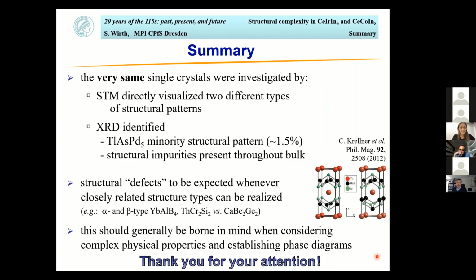Yes, actually, you have to be a little bit careful here. What we saw over the course of many years is that little nuances can pretty much influence the cleaving behavior. I have shown you that the cerium cobalt indium-5 actually cleaves pretty easily, at least along the 001. But in the example of the 122 structure, for instance, we have lots of experience with ytterbium rhodium 2 silicon 2, which cleaves nicely. But if you go for cerium copper 2 silicon 2, the very same structure, silicon based and not that much changed, it doesn't cleave at all.